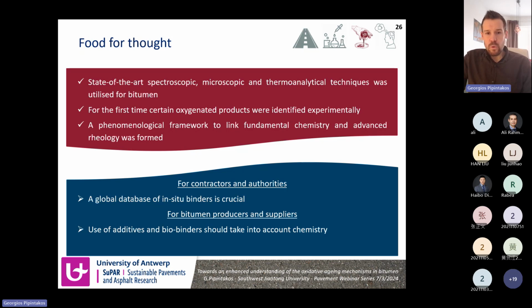Also, we should be able to link this information with the performance at the end. So the chemistry should be linked with the rheology of bitumen, since we should couple the chemistry with rheology for engineering purposes. So from this presentation, what is important is that for contractors and authorities around the world, we should propose as a scientific community a database of in situ binders. In situ binders means binders extracted and recovered from asphalt cores, because this includes all the information as it happened in reality. Whatever we try in the lab, oxidation kinetics or lab simulations, they still do not capture all the effects of aging that happen in situ, in the real road, in the field.